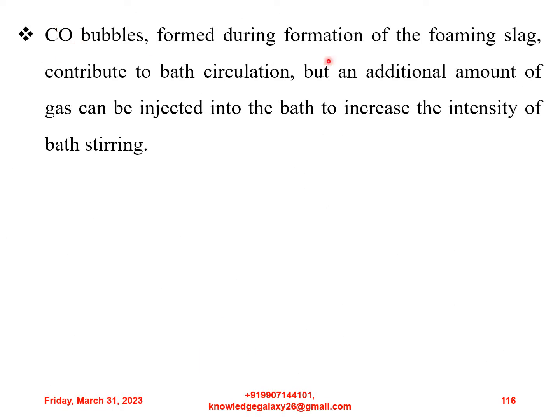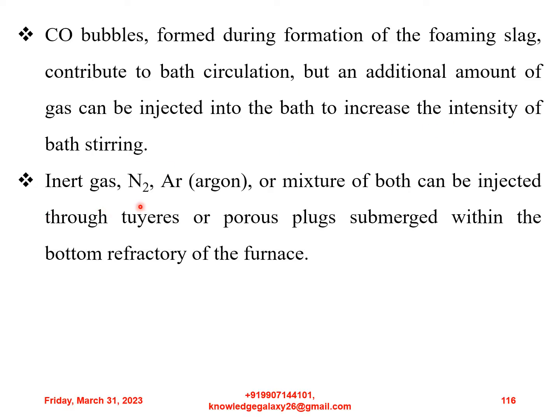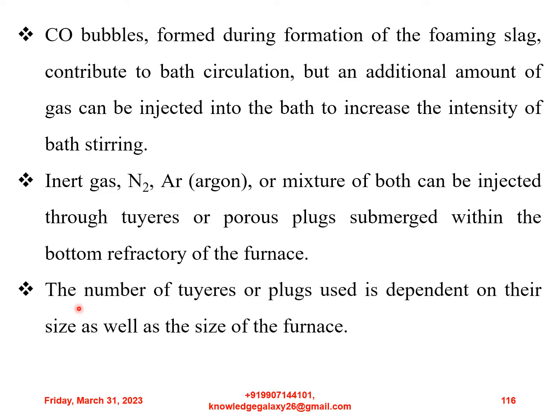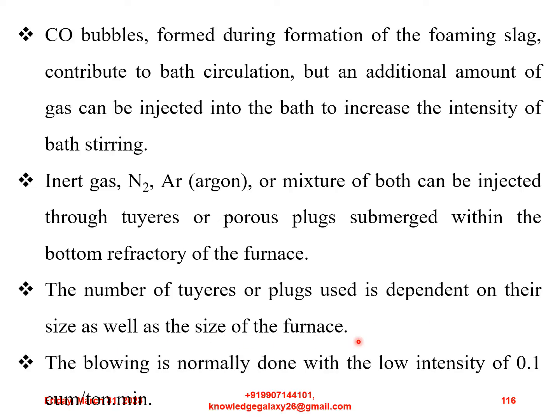CO bubbles formed during formation of the foaming slag contribute to bath circulation, but an additional amount of gas can be injected into the bath to increase the intensity of bath stirring. Inert gas like nitrogen, argon, or mixture of both can be injected through tuyeres or porous plugs submerged within the bottom refractory of the furnace. The number of tuyeres or plugs used is dependent on their size as well as the size of the furnace. The blowing is normally done with the low intensity of 0.1 cubic meter per ton minute.